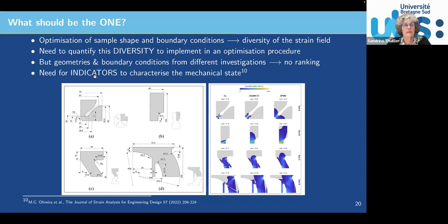So in this case, we need indicators in order to characterize the mechanical state, because the idea is that we want a rich mechanical state. So how can we define indicators? So indicators, you've got here a distribution. So I forgot to mention, in this case, it's a numerical study. So what you can see here are the results of the finite element simulation, considering 3 different materials: a pure copper sheet, an aluminum sheet, and DP600 material. Although it's virtual, real materials were considered, and so material parameters come from real materials. So the idea was, beware, as I mentioned previously, as localization may depend on the material, it's interesting to investigate several materials at the same time.